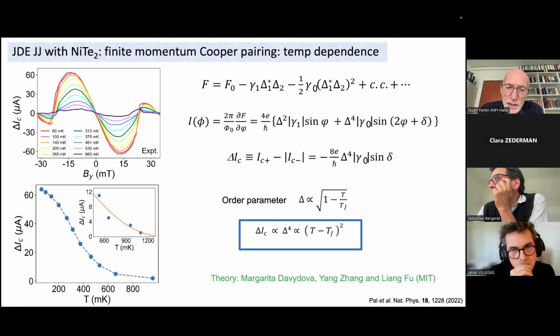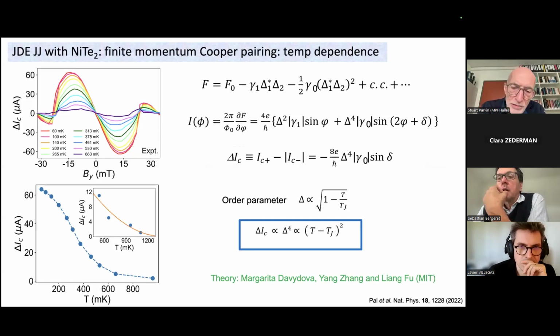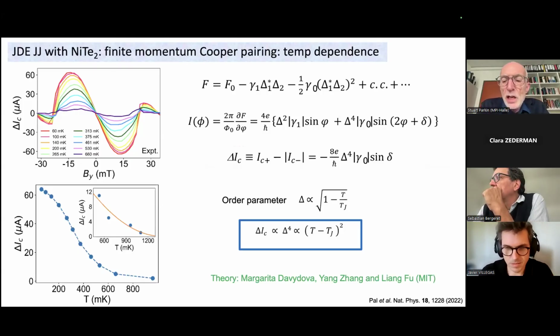With the increasing field, that spin splitting increases, and the electrons pick up more phase, and this gives rise, through the standard current phase relationship, to nodes in the delta IC as a function of increasing magnetic field. What was also very nice was that they could calculate the dependence of this diode effect, the difference in critical current for left and right, as a function of the superconducting order parameter and how that relates to temperature.